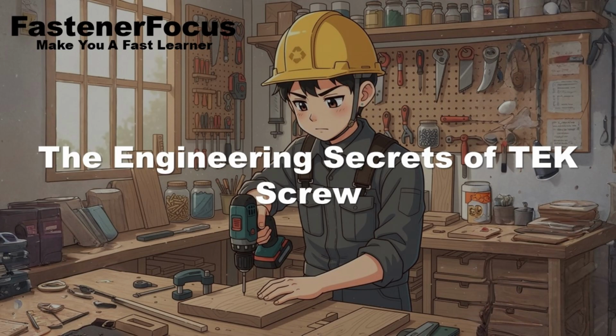Then we move into the truly corrosion-resistant grades. That takes us to austenitic stainless steel grade 304, or A2. This is the general-purpose, cost-effective corrosion workhorse. It contains significant nickel, typically 8% to 10.5%, which stabilizes its structure and provides excellent general corrosion resistance. It's also highly ductile. But I read that 304 cannot be heat-treated to gain strength. That's right. Austenitic steels cannot be hardened through quenching and tempering. Their strength comes primarily from work hardening during the thread rolling and cold forming processes. And what's the major limitation of 304?